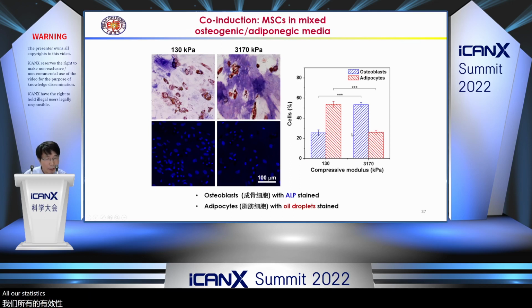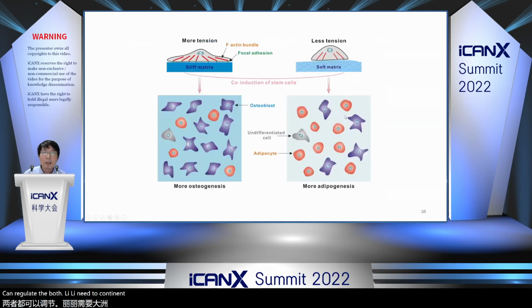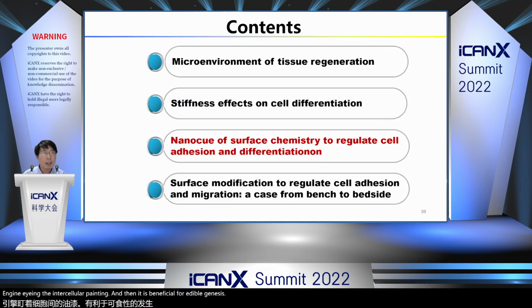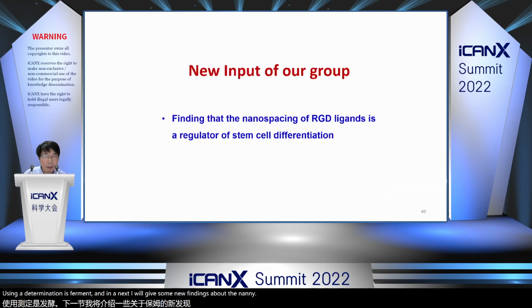Our statistics indicated that matrix stiffness can regulate both lineage commitments. We also give a preliminary interpretation: the stiff matrix could lead to more tension, so it is beneficial for osteogenic differentiation. Meanwhile, the soft matrix leads to less intracellular tension, and then it is beneficial for adipogenesis. Now we have confirmed the matrix stiffness effect using a deterministic experiment. Next, I will give some new findings about the nanocues. The new input from our group is that we found the nano spacing of RGD is a regulator of stem cell differentiation. No one realized this before we published our paper.